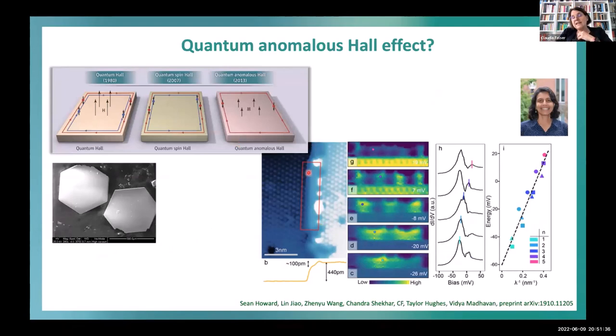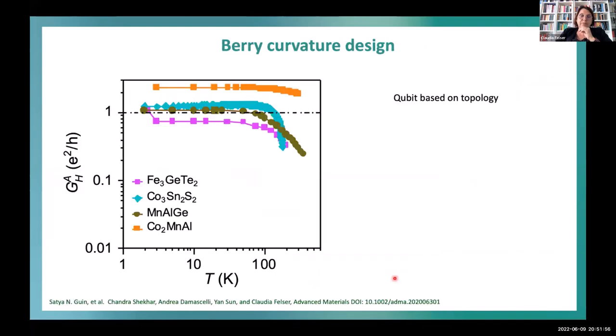But also, if you look with STM at the edges of Co3Sn2S2, you have chiral edge states, and the chiral edge state shows a nice quantization if you bias it. So it's already showing evidence that we can have chiral edge states, and we can maybe have it at much higher temperature in the future. And here it's like what I mentioned. So if you take the anomalous Hall value and divide it by the number of layers in your crystal as a function of temperature, you see that these materials which are more quasi-two-dimensional and topological are coming very close to the quantized value.